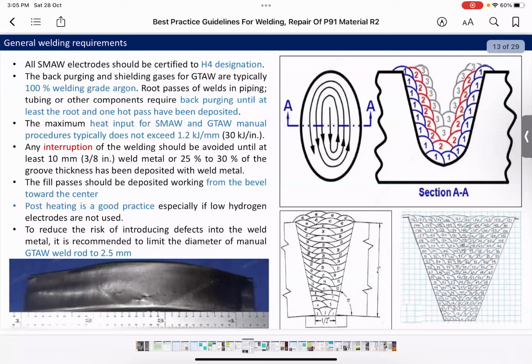Post-heating, as I said, is a good practice, especially if low hydrogen designation is not used for filler wire. And to reduce the risk of introducing defects for the root pass, the filler wire should be limited to 2.5 mm. Okay. In this photo here, we see that during the bend test, the sample failed the bend test using 4 mm filler wire size, and this is why we should limit welding the root pass to 2.5 mm filler wire.